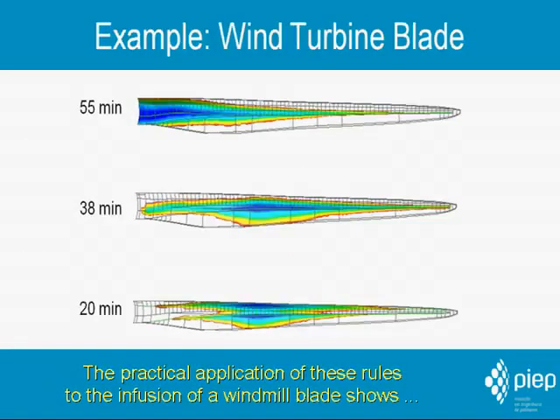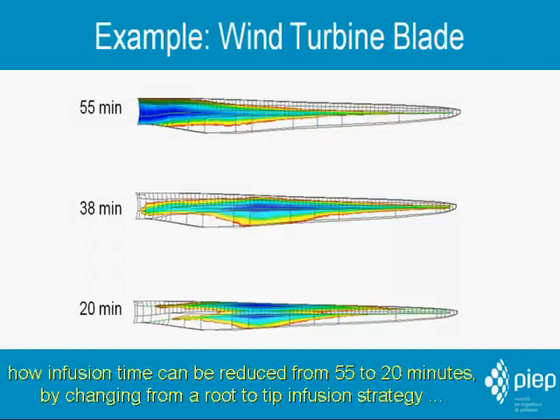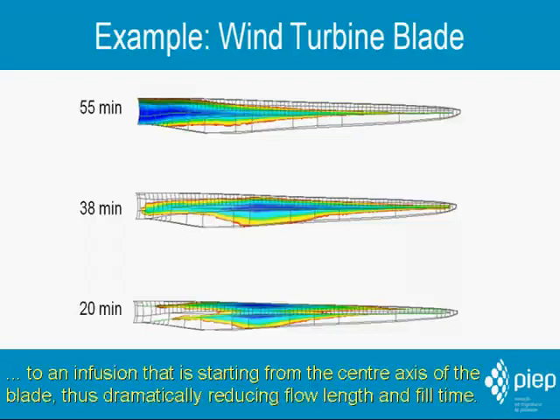The practical application of these rules to the infusion of the windmill blade shows how infusion time can be reduced from 55 to 20 minutes by changing from a root-to-tip infusion strategy to an infusion that is starting from the center axis of the blade, thus dramatically reducing flow length and fill time.